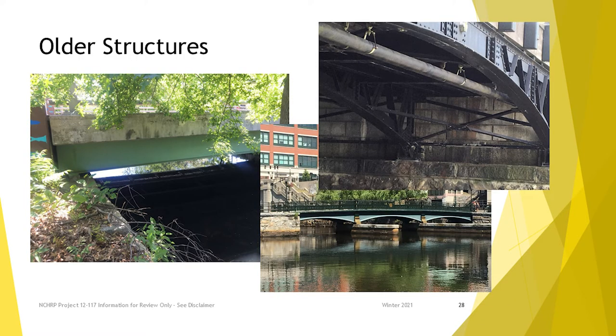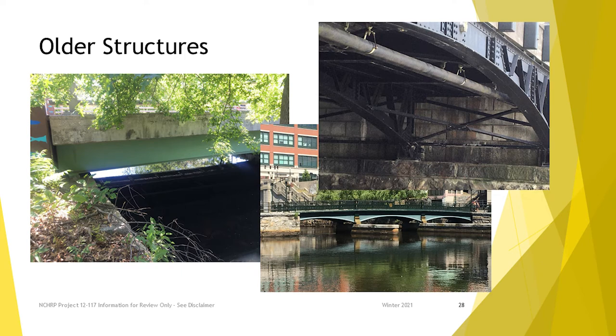My favorite was this one — almost 30 years old when we looked at it. It's a small historic arch bridge in a kind of expensive residential area. They disassembled it, took it to the galvanizing plant, galvanized it, painted it, and brought it back and reassembled it. It's insane that they did that. With the exception of the railings right around where de-icing salt would be, and one little spot underneath the expansion joint, it was in great shape after 20-plus years.